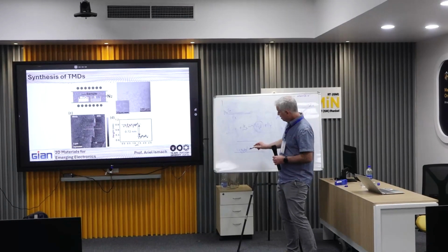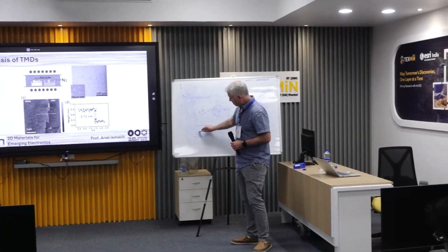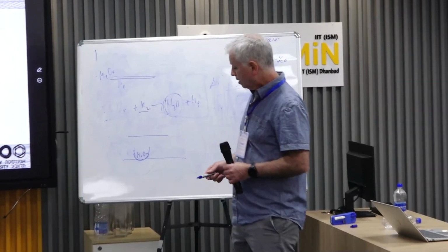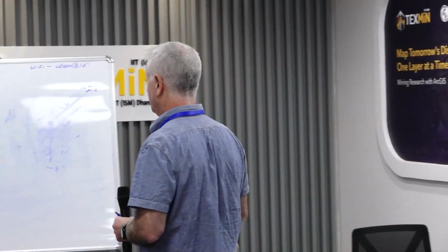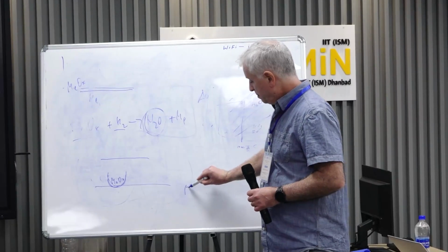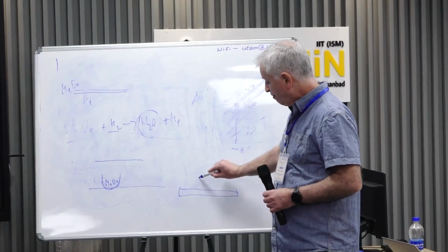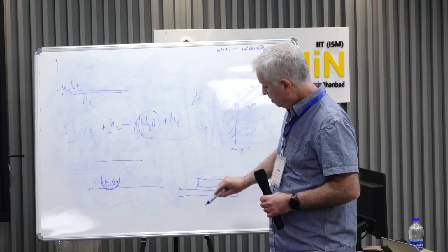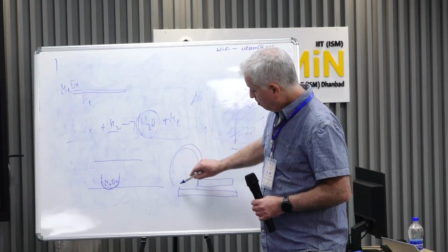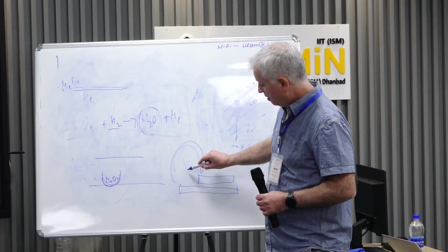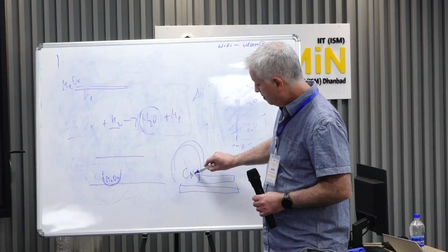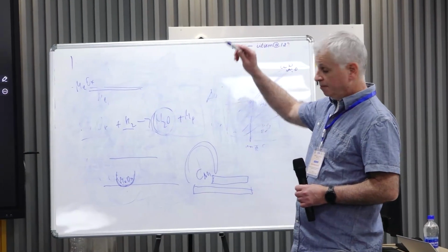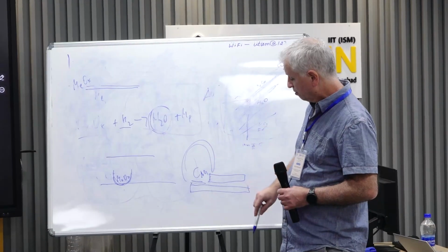The first one that I discussed, for example, is to work in a condition in which we know that we have high evaporation rates, but then to confine the area of the growth. So here we have a stable and constant, very high concentration of the precursor, in an area that is confined.